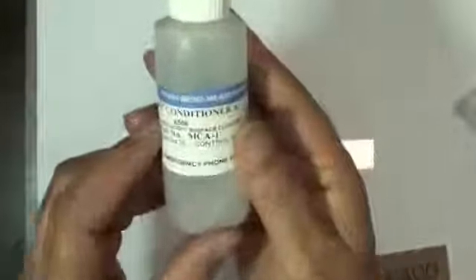To do this step, Vijay is going to use the 400 grit wet or dry silicon carbide paper. The M-Prep Conditioner A is a mildly acidic solution, highly pure, in a one-way container, so it's not going to contaminate or become contaminated. This has the effect of removing oxidation from the surface. It can also emulsify some organic materials that could remain on the surface after degreasing. The 400 grit abrasive is going to give us the correct surface finish that's recommended for aluminum. We're creating some peaks and valleys, increasing the surface area so that the gauge adhesive has plenty of area to make contact with.